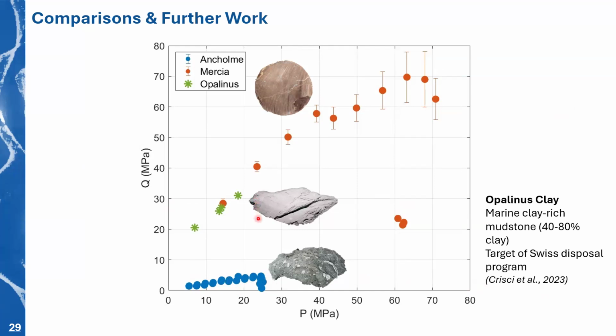I also put on comparison, we don't have very many literature sources of similar measurements, but there have been measurements by Silvio Geiger's group in Switzerland on the Opalinus Clay, which is the target for the Swiss disposal program. So I've put these points on in green for the Opalinus Clay, and they actually overlap quite nicely with our Mercia mudstone. It may be that they fit better with the Mercia mudstone sample because they're both recovered from cores, whereas our Ancholme Group sample is a surface-derived sample. So it may be that the source of the different rock types has impacted the mechanical data that we're recovering.